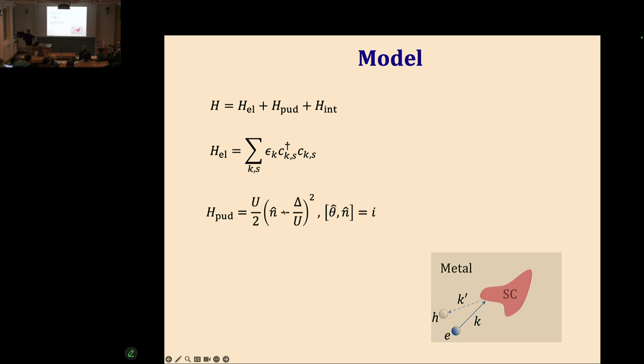And moreover, because of the landscape of the disordered potential, this superconducting island likes to have a certain charge. So there's some background charge that the system likes to have in the ground state, and this number doesn't have to be an integer. The ground state of the system would be the closest integer n to this background potential, basically. So this is what the energy levels of an isolated island would look like. They're parabolic in n, and we have the two lowest energy levels, n0 and n0 plus 1, that are separated by this energy delta.